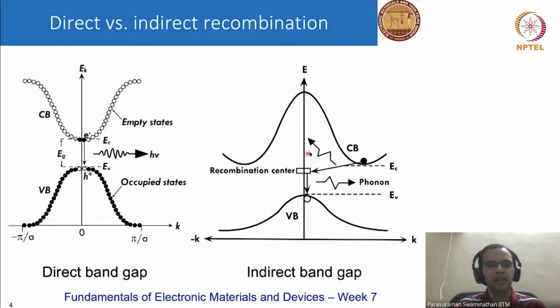On the other hand, when the electron in the conduction band recombines with the hole and the energy is given as heat, it is called an indirect band gap semiconductor. Silicon and germanium are the most prominent examples of indirect band gap semiconductors. When we want materials for optoelectronic devices that primarily emit light, we need direct band gap materials.